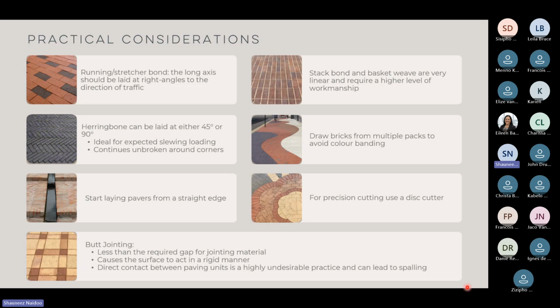Corobrik also offers a full range of special shapes. Butt jointing is less than the required gap for jointing material. It causes the surface to act in a rigid manner, and direct contact between paving units is a highly undesirable practice and can lead to spalling, which we've often viewed on site, and they say that the pavers are failing. When you look, the pavers are butt jointed, which is not recommended.